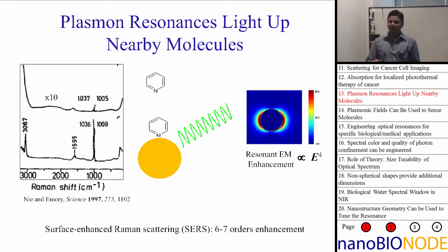Silver turns out, as you saw in the first video that I showed, silver is much more intense at scattering light. Those of you, maybe someone here is an electrical engineer, silver is a very high conductivity metal. It has a very low resistance. And it turns out the same principle applies to a plasmon resonance. These electrons that are oscillating don't want to have too much resistance to their motion. And so in silver, there isn't much resistance to the motion of these electrons, and so the quality of the plasmon resonance mode is higher, meaning the scattering cross sections are much higher. So same size of silver particle, silver scatters a lot more light.